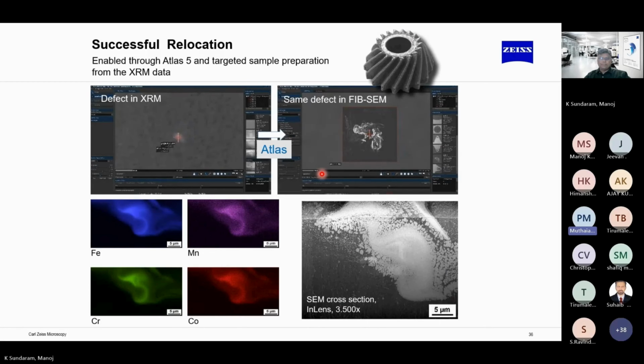This is another example of the correlative workflow. We identify a defect in an XRM, and on the FIB-SEM, we do the material removal and the imaging. Post imaging, the right-hand side bottom image is the SEM image, and on the left-hand side, the 4 colored images are the chemical composition, or chemical mapping, of the contaminant, where you can see ferrous, manganese, chromium, and cobalt present in the aluminum printed part. So how does a contaminant with this composition come to be present in the aluminum printed part?